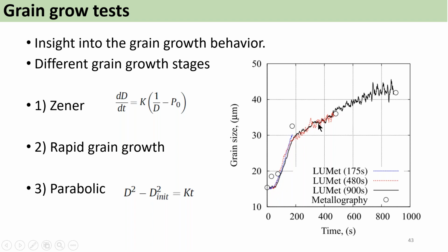So here it's not like the example I showed you before. The bulk of the sample is large enough that we have very good repeatability in the grain size, although the occurrence of abnormal grain growth is present. And so we try to go a little further in analyzing the different stages of grain growth. You can see there are stages of very low growth rate, where the grains are pinned by the precipitate; a stage of rapid grain growth, where the precipitate dissolves heterogeneously in the microstructure; and then we come back to a stage of normal grain growth, in which the precipitate is fully dissolved in the structure.